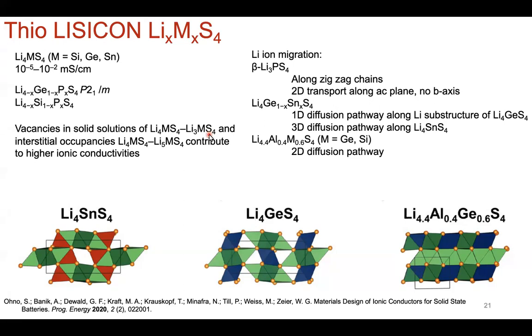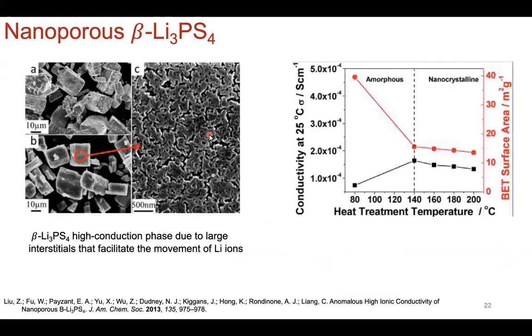Okay, so that's very interesting. In terms of nanostructuring, this is a highly cited paper. It was exciting to see for a number of reasons. One, ion conductivity is increasing, but also two, the low temperature reaction conditions of lithium thiophosphate, particularly this beta phase that doesn't exist outside of the synthesis, or you can't access this phase via solid state conditions.